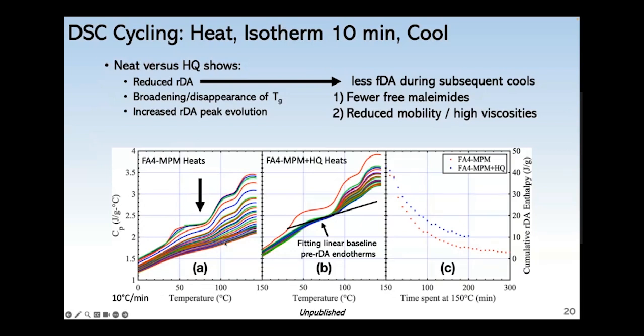After about 30 cycles, the RDA peaks completely or almost completely disappear. And then another interesting observation is that the Tg broadens out after a few cycles, and then it eventually disappears. In plot B, I show the same procedure, but using the hydroquinone additive. And you'll see there's a much more gradual disappearance of those retro Diels-Alder peaks. And in the final plot, I integrated the heat capacity to calculate the enthalpy from the RDA peaks. And this again shows that the sample with hydroquinone still forms more Diels-Alder bonds for the same amount of time spent at 150 C.